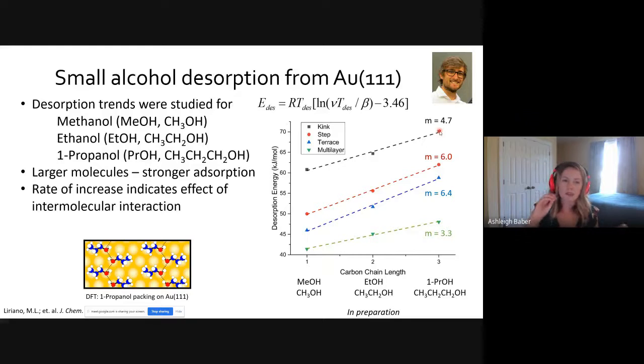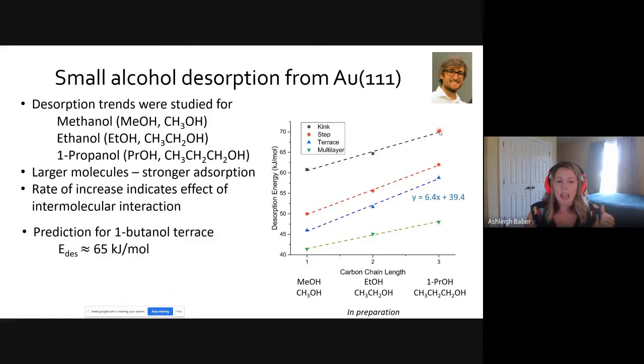So again, I'll just reiterate that a molecule sitting out on a kink site is kind of on its own. And so you don't have that maximized intermolecular interaction that enhances and increases its desorption temperature. And so we can start to predict, okay, where do we expect 1-butanol to desorb from the surface? Well, we can say it's going to be around 65 kilojoules per mole just based on the slope of this line.